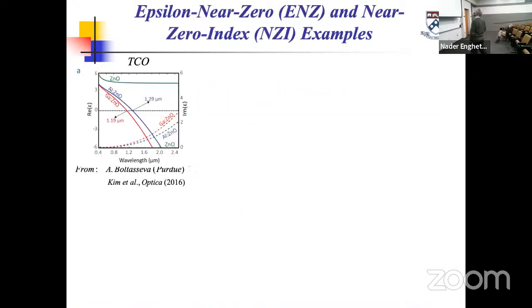Okay. So what are these materials? There are actually several good examples of that. If in the near IR, you can look at transparent conducting oxide, indium tin oxide, aluminum doped zinc oxide, gallium doped zinc oxide, you notice that if you look at around the wavelength of 1.29, 1.19, they have a zero crossing of a real part of permittivity. Of course, the imaginary part is not zero, and we would like the imaginary part to be very small. So for some application, these materials are good, and some other ones, not necessarily.